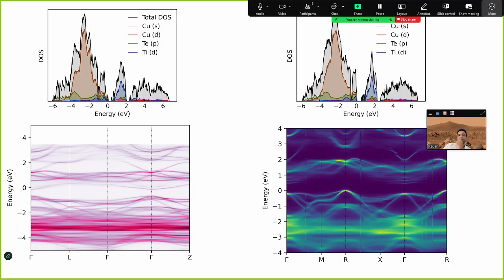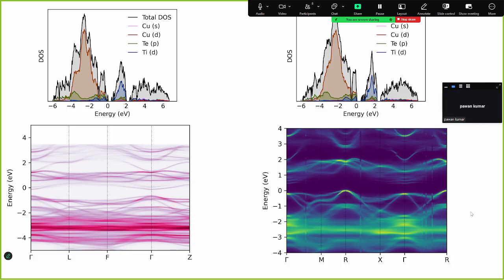So you don't have a dispersive band, you have very broad bands, like an oxide. Can you ask Andy, who did the band structure, for the effective mass values? Pawan can help you do the analysis. The only question that remains is whether the intrinsic effective mass is low or high. If it is high, then the intrinsic mobility of the material will be low.